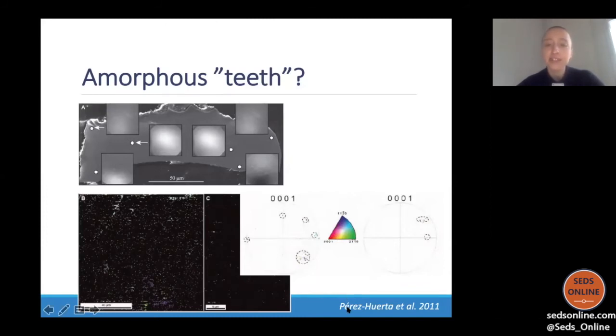There was one attempt by Alberto Perez Huerta, who is a very talented EBSD and biominerals worker, and I have been learning a lot from his papers. But when he tried to analyze conodonts, he ran into a problem that we were able to reproduce, which was that he was not getting any signal. These squares here, this is where you should be seeing Kikuchi patterns. You cannot see anything, and he got maybe 20 data points. That's not enough to analyze. And so he concluded maybe they were amorphous, which would be very interesting, but I was suspicious of this because you can see them polarized under the light microscope.